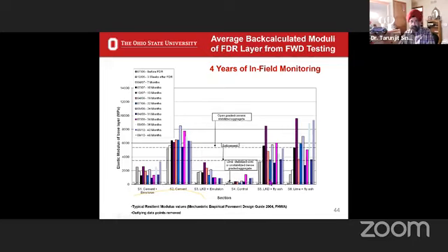So the cement section, the LKD and fly ash, and the lime and fly ash section are the three that we want to focus on, because this is what is commonly used, not the control. As you can see, suddenly it increased, went up. Now, if you look up here, you can see winter months are coming, right? The resilient modulus, or the elastic modulus, does not remain constant. It is a function of temperature and weather. So there is curing happening. So depending on when they are done, one has to compare them.